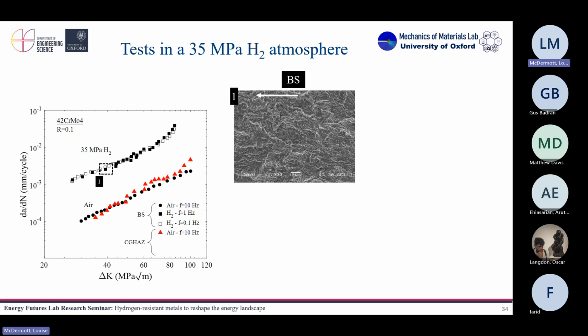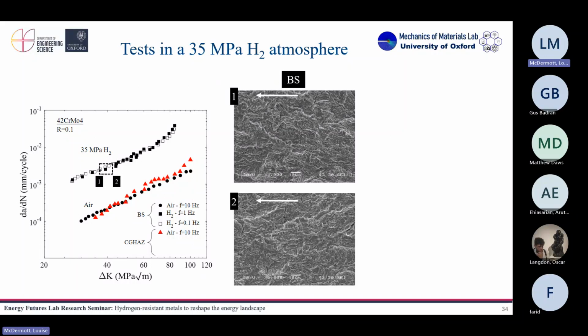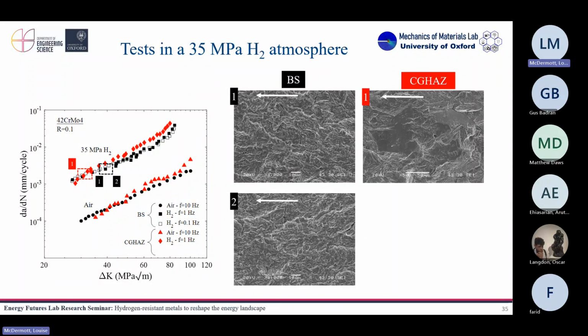And I said, okay, let me see if there is any effect of fatigue. So I reduced the frequency even more to have the same frequency as we had in the other experiments, and the curves were overlapping. So I said, okay, it's weird, interesting. In this kind of experimental procedure, there is no effect of frequency. And of course, again, I observed no, let's say, ductile behavior during propagation. So then what I did was, okay, the same in the weld, and I obtained exactly the same trend. So no difference in the curves between different frequencies.